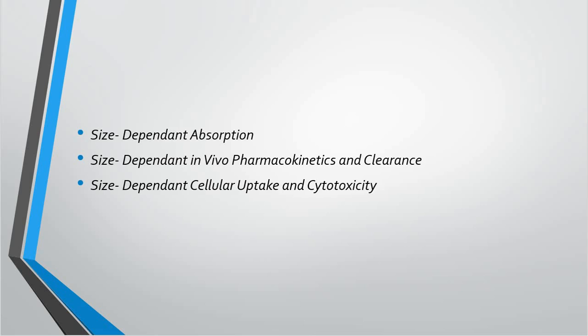Most nanoparticles that accumulate in the liver and spleen cause serious side effects. For instance, cadmium selenide quantum dots remain in the tissue for up to 8 months and cause hepatotoxicity. This pharmacokinetic characteristic of nanoparticles is dependent on particle size and surface chemistry. Next is size-dependent cellular uptake and cytotoxicity.